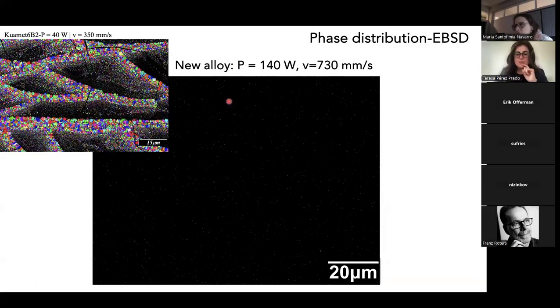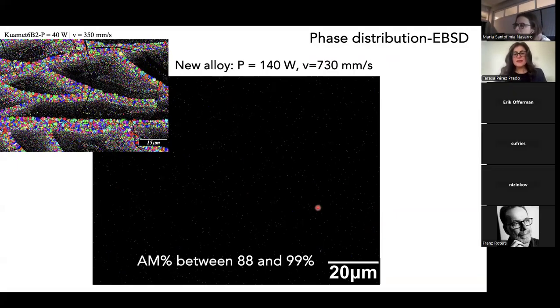Then we did EBSD, and again, I bring back the EBSD map that I showed you before corresponding to the commercial alloy, and here by EBSD we get a completely black map. So this was also looking good. And we measured by DSC the amorphous fractions, and within all this processability window they range from 88 to close to 100%, to 99%. So this was also very good news.